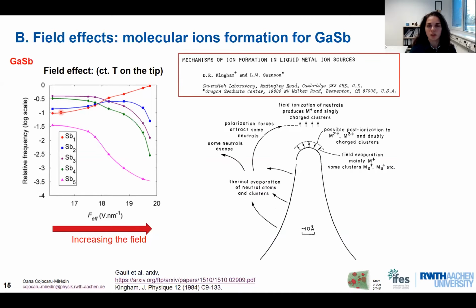And there was a very old model given by Kingham and co-workers about the mechanism of ion formation in liquid metal ion sources. So what is a liquid metal ion source? It's an ion source which uses metal that is heated to the liquid state and used to form an electrospray to form ions. So an electrospray Taylor cone is formed by the application of the electric field, and ions are of course produced by field evaporation. And this is exactly what happens in the focused ion beam for the gallium source. So why was gallium chosen? Simply because gallium has a very low melting point and a low vapor pressure.